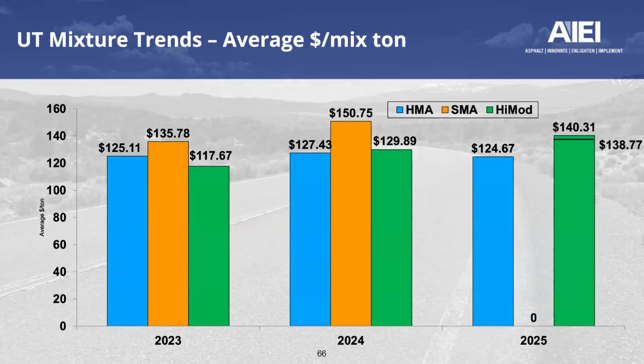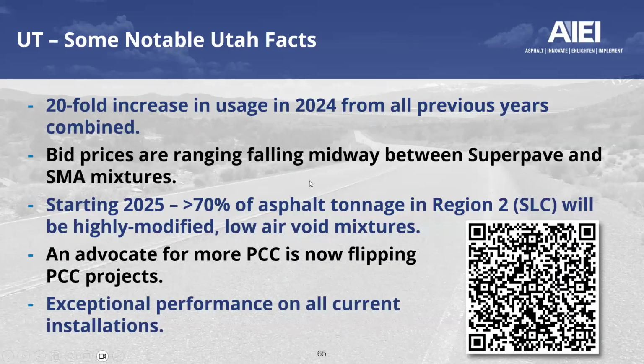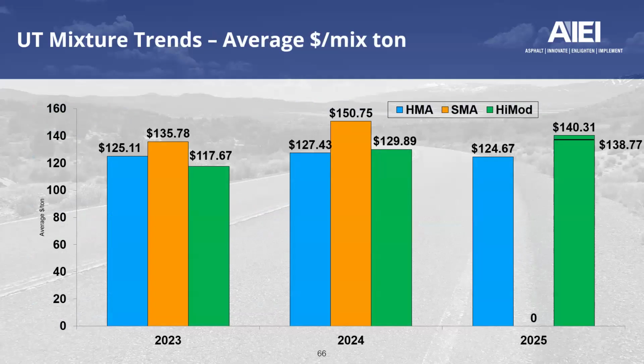In terms of cost, Howard Anderson was kind enough to provide me with cost data. I'm showing you a comparison between the typical hot mix asphalt, that's going to be a Superpave 6434 SMA, which was once the dominant mixture for high stress locations within the state of Utah, and finally the highly modified materials. Notice that in 2023, the cost of the high mod actually was less than the 6434. That in part can be primarily related to most of the projects with the high mod had relatively short haul distances, and so additional cost was encumbered by Superpave in terms of haul. That isn't directly reflective of the material itself, but since we did not have the ability to filter that out in those projects, we see the raw numbers of 125 and 117 respectively per ton.